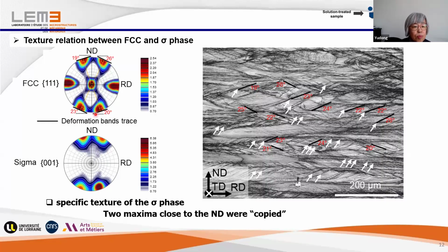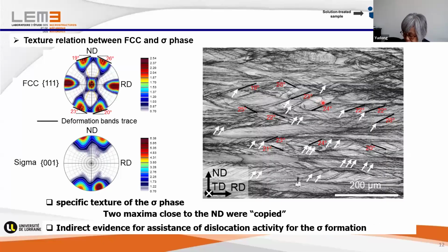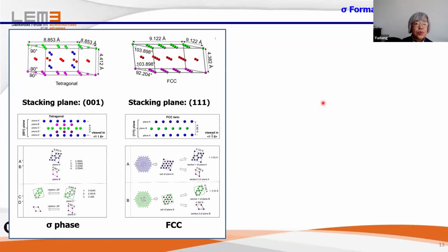And these two pairs, the orientation really corresponds to the angle range of these slip systems, the 111 planes. So that means we can make an atomic link between the two structures. So we can go deeper in the analysis to see how the passage happened from this structure to this structure.